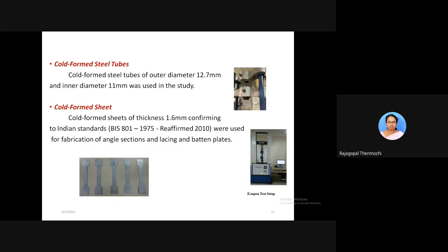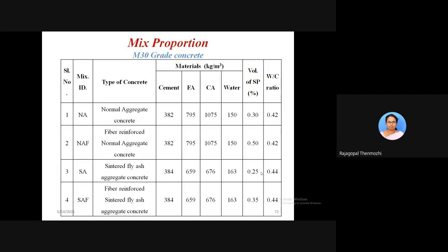As usual, before starting the testing, we have to test the cold formed steel tubes and the sheet also, because we have used the lace and batten system using cold formed steel. As per IS 801 1975, reaffirmed in 2010, we have checked the standards for the steel. These are the different mix proportions for the M30 grade, because nowadays M15 is obsolete. M20 exists only for PWD people, but for mega projects, people have started shifting to M25 and above grades to make slender sections. So if any of you have started your research now, don't go for M20 or M25. Please go from M30 onwards, because the code is getting revised quite often. By the time your research ends, it will shift to the next grade.